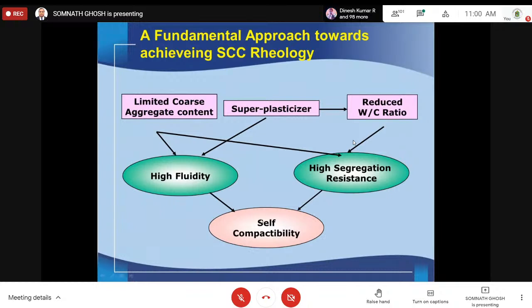Otherwise, you just can't. Because here, concrete is just like a fluid. The slump, etc., you can't compare with conventional concrete. Even if you can't measure slump, it is just like fluid. But you will be able to achieve it at a very, very low water cement ratio. And obviously superplasticizers, viscosity modifying admixtures, these things have a very important role. So you have to procure these things and you have to cook it properly. Then only you will be able to achieve self-compactability.